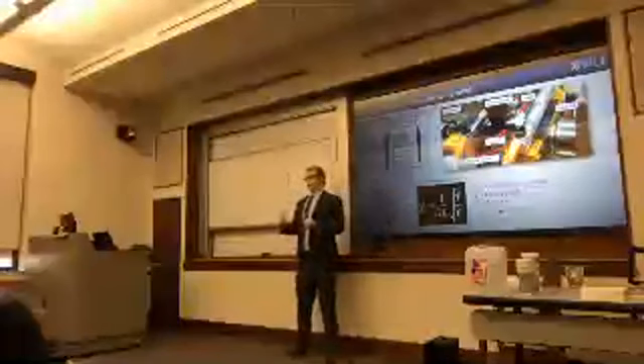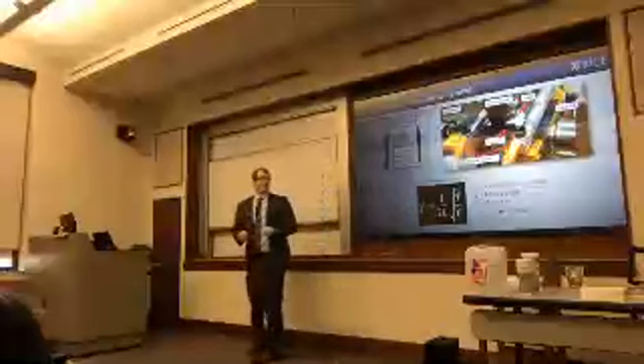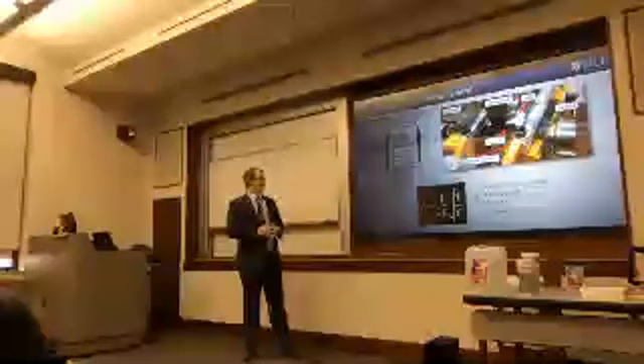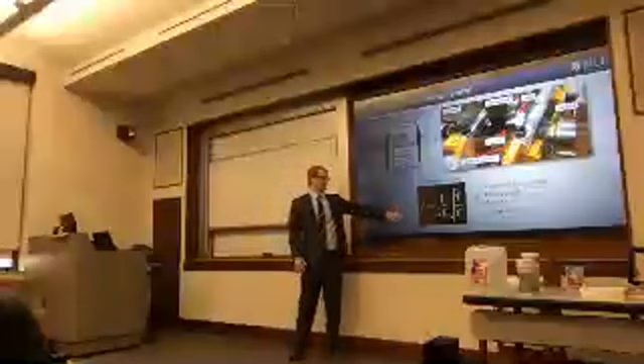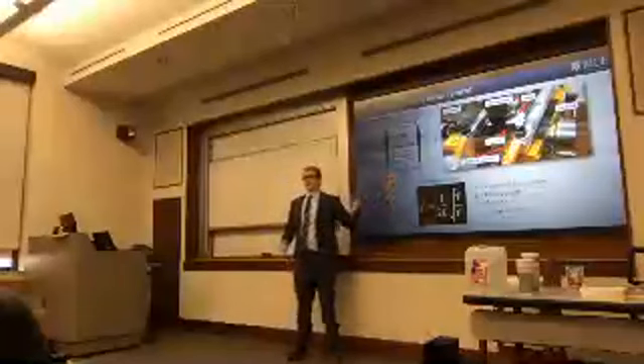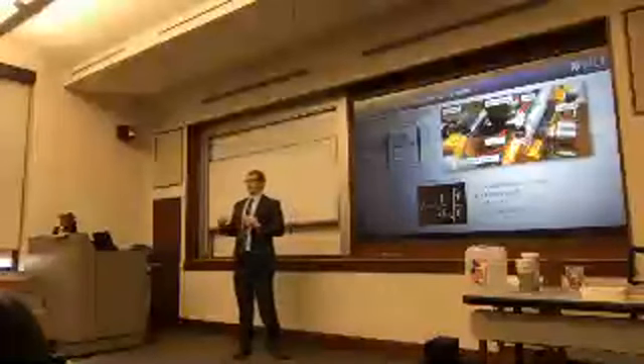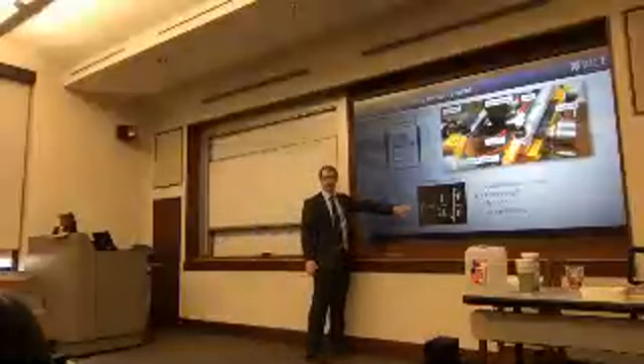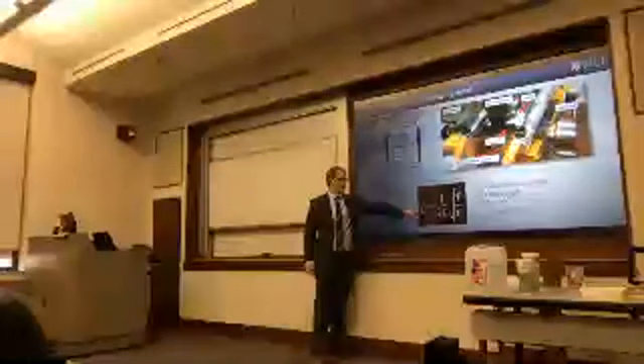And so the way that we accomplish this is by taking the fiber and suspending it over a permanent magnet. On one end, we have a motor so that we can pull on the fiber. And on the other end, we have a load cell so we can measure the tension that's on the fiber. We then send an alternating current through the fiber at many different frequencies. And as we pull on the fiber, eventually it will come into resonance, dependent on this equation, and it will start to vibrate due to the presence of the permanent magnetic field. The vibration of the carbon nanotube fiber produces a sound that we can record with a microphone. So we take that sound, we analyze the frequencies, we know the length because we chose that, we measure the tension with the load cell, and now we can back calculate the linear density.